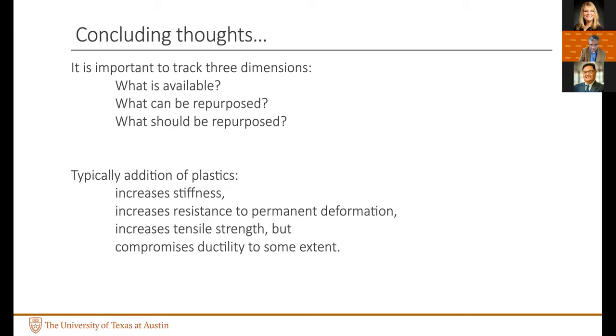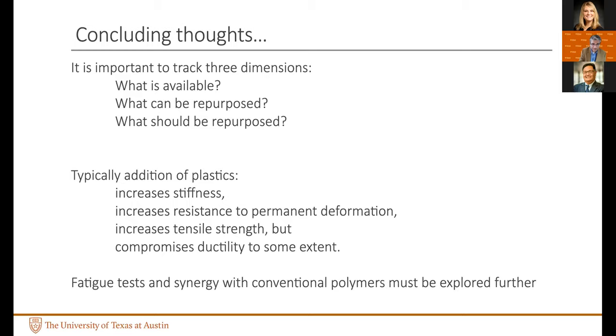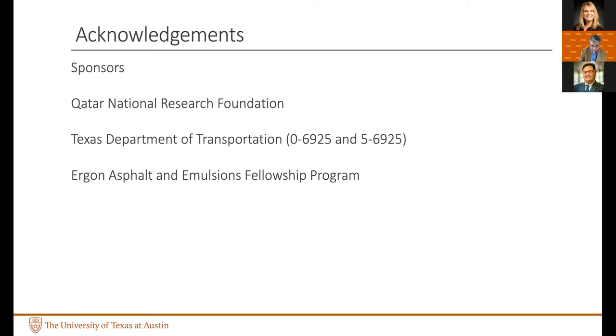And typically with our preliminary results with LDPE, what we see is an increase in stiffness, increase in rutting resistance, increase in tensile strength, but it comes at a cost of a little bit of loss of ductility. Whether the two offset each other for a zero or net gain in performance, we can run a few more fatigue tests to establish better. That was the last point, is that we're in the middle of this project and we hope to get more results in time.